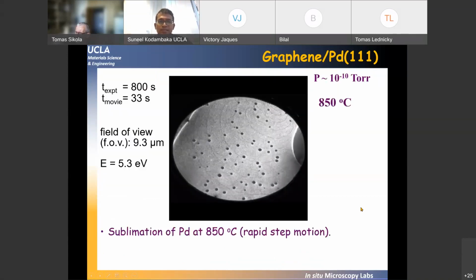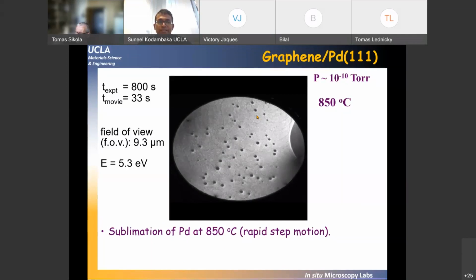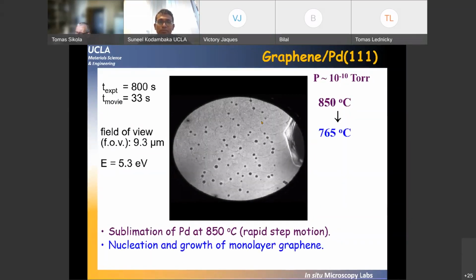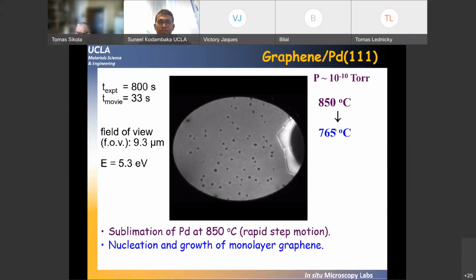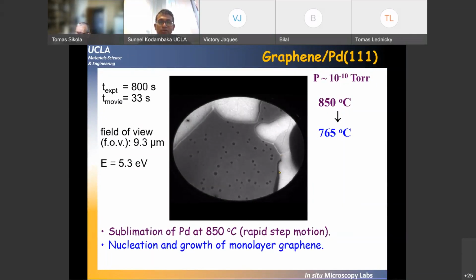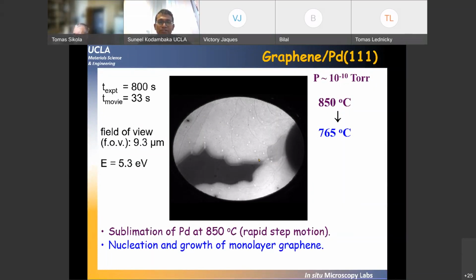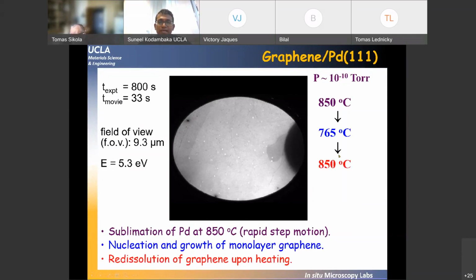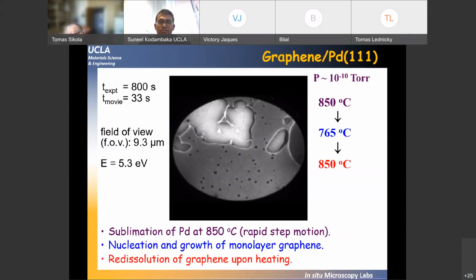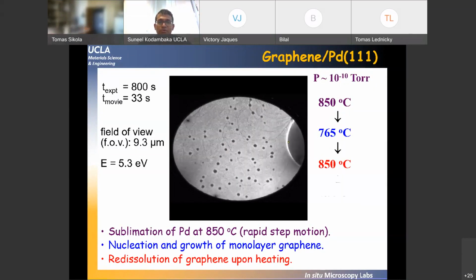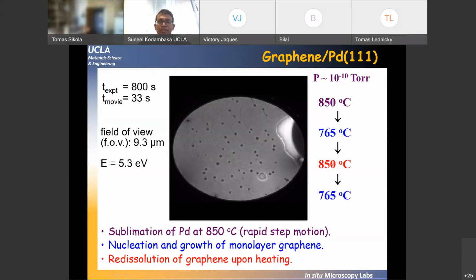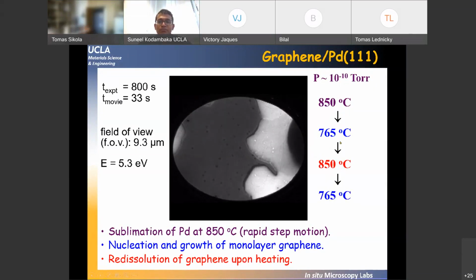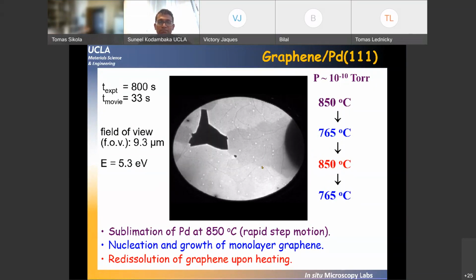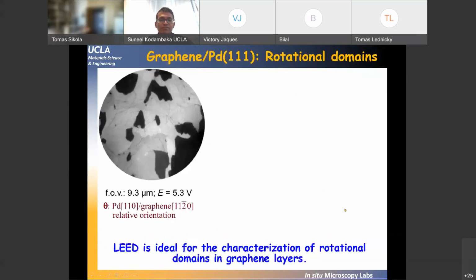Okay. So this is the LEEM movie that's obtained while annealing a palladium crystal with a lot of carbon dissolved in the bulk. As we cool it down, the carbon starts segregating on the surface in the form of graphene, and you see the graphene layer growth. If you heat it back up, the carbon redissolves and goes back into the bulk, and now you have a clean palladium surface. And again, this process is repeatable, so if you heat, you dissolve the graphene, you cool it down, you get graphene back on the surface. And we use this to our advantage to form monolayer graphene.